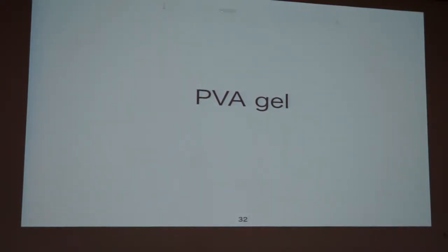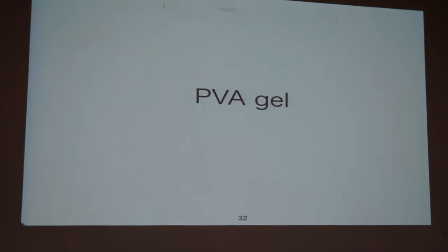That sort of phenomenon can only be observed in PVA or other polymers. PVA gel, we investigated this gel more than 15 years ago, and it showed very efficient deformation. The reason why we don't use this gel for practical application is that solvent leak is inevitable in this gel. Also PVA is a hydrophilic polymer, and we use the DMSO solvent. DMSO is also easily contaminated with water and other contaminants from the environment. So the reproducibility is not that good. So that's the reason why we didn't use this gel for actuators.